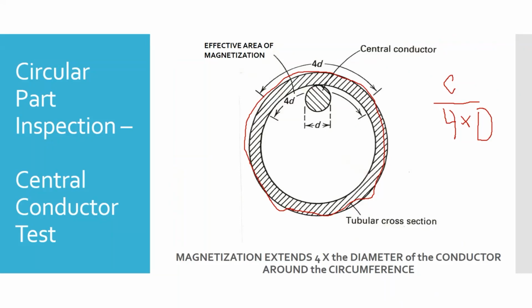So you can see why having a thicker rod might be a little bit better. If you can fit a larger diameter non-magnetic rod, you would have to turn it fewer times. But you could still do a really big part with a really skinny center conductor. You just might have to turn it 8, 10, or 12 times, right? So you just got to keep that in mind as you're doing that, okay?